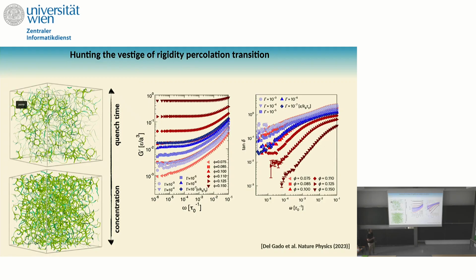You would get different microstructures, and then plot, for example, G prime as a function of omega for all these systems. So the red one is the one where you change the volume fraction, and the blue one is the one where you fix the volume fraction and you change the preparation protocol or the kinetics. So here I'm putting G prime, here I'm putting tan delta, which is just G double prime divided by G prime. And you see that you recover similar phenomenology as the one that I showed you in the experiment. But the question is, can we understand where this power law is coming from?